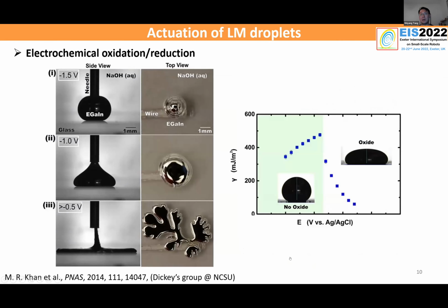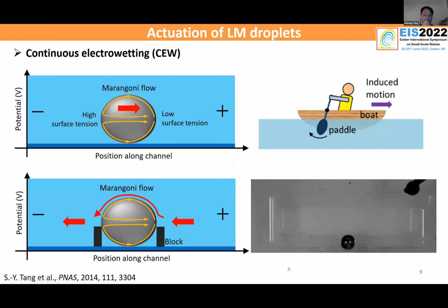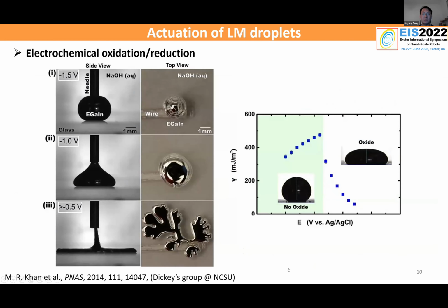These two principles are fundamental to many of the actuators we developed later on. Another principle we harnessed was discovered by Professor Michael Dickey's group at NCSU. They found that if you oxidize a droplet of liquid metal, you kill the surface tension because you form an oxide layer on the surface. The oxide layer acts like a surfactant in an oil-water system.